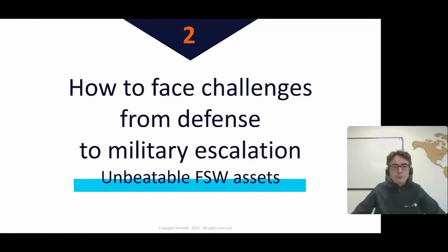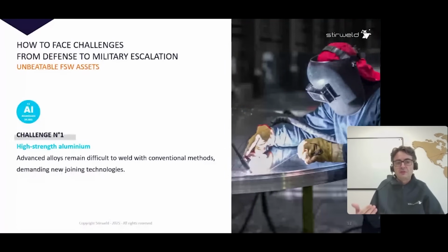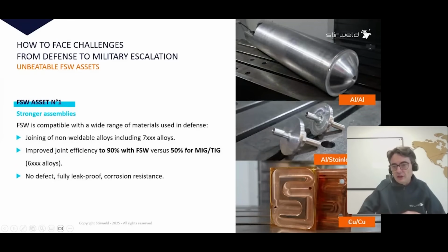Part 2 of my presentation now is why friction stir welding is interesting for defense applications. In the defense sector, we meet different challenges. The first one is that we have to weld high strength aluminum, for example 6000, but also and mainly 2000 and 7000 aluminum alloys. By friction stir welding, we can weld any kind of aluminum alloys, including the non-weldable alloys, such as 7000 alloys. For example, 7075 T6 alloy can be welded using FSW without any problem.